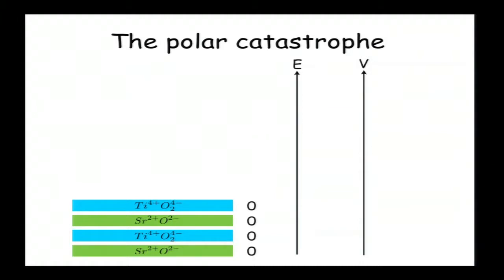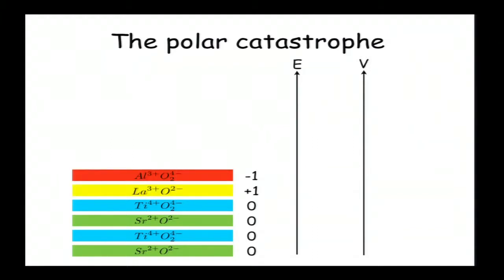Now, it is important to notice, if we are looking at the ionic composition of this material, that strontium titanate has this layered structure that we saw before, and each layer is charge neutral. But when we are growing a layer of lanthanum aluminate on it, unlike strontium titanate, lanthanum aluminate has one extra electron in the aluminum oxide layers per aluminum atom, and one missing electron in the lanthanum oxide layer per lanthanum atom.